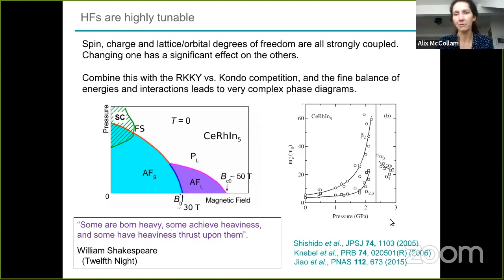And this is one of the most famous experiments, I think, that we have in the heavy fermion systems. This is the effective mass measured via the de Haas-van Alphen effect at high pressure, and showing that there's a divergence of the mass here associated with the change in the Fermi surface from this antiferromagnetic phase to the paramagnetic phase.